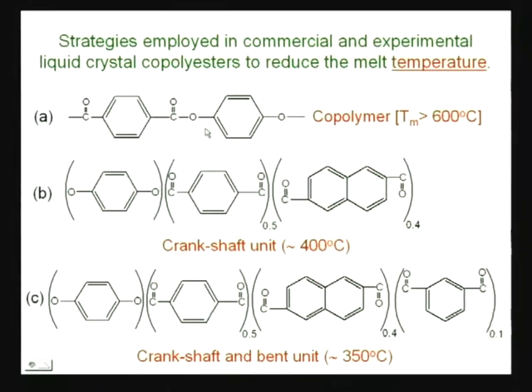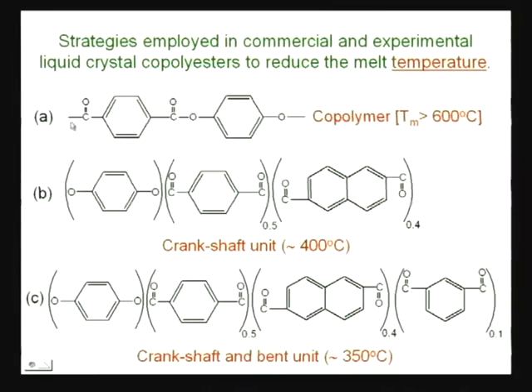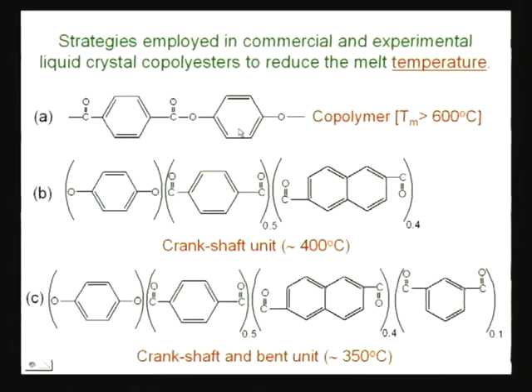So, you see why here you can get also again the correlations between molecular structure with its property. This melting point is a property. How the melting point is related to its structure, you can understand this thing, and which is again related to molecular order. That means, it will give you more packing, as well as the backbone chain contains rigid phenyl ring. You have seen in case of polystyrene that rigid phenyl ring remains as a pendant group. Here this phenyl group is present along the backbone chain. So, whereas polystyrene melts above say 120, 130 degrees Celsius temperature, this polymer melts quite higher than 600 degrees Celsius temperature, and the reason you can understand. Clear?